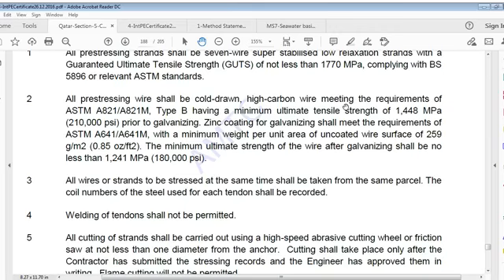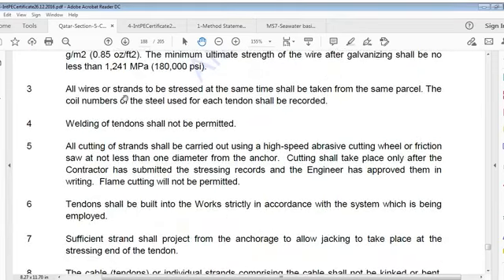Zinc coating for galvanizing shall meet requirements of ASTM A641/A641M with a minimum weight per unit area of uncoated wire surface of 259 gram per meter square, 0.85 oz per feet square. Minimum ultimate strength of wire after galvanizing shall be no less than 1241 MPa, 180,000 psi.